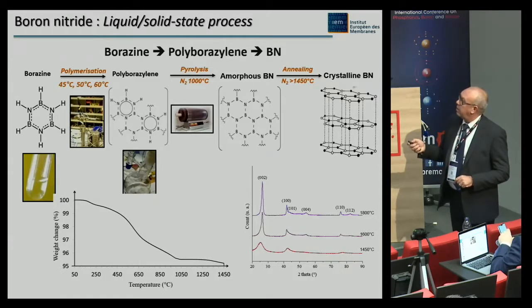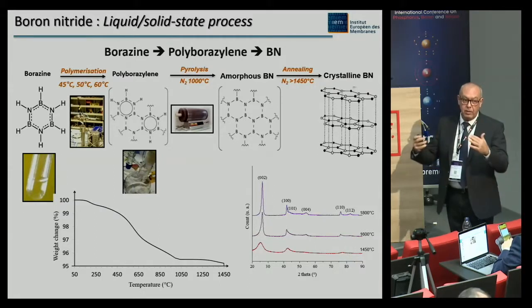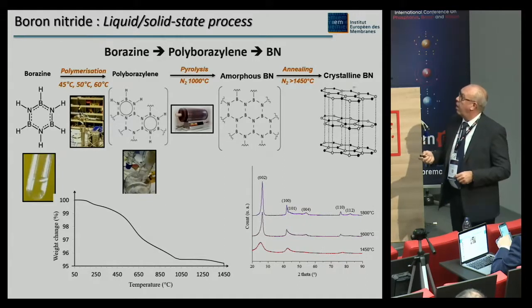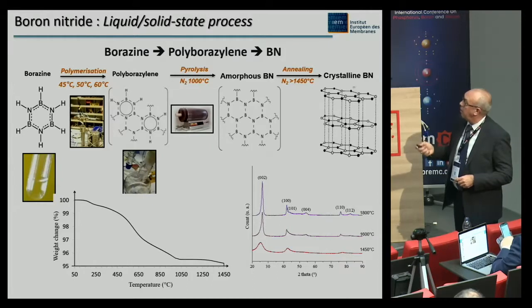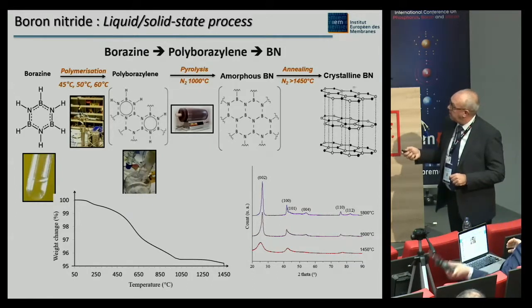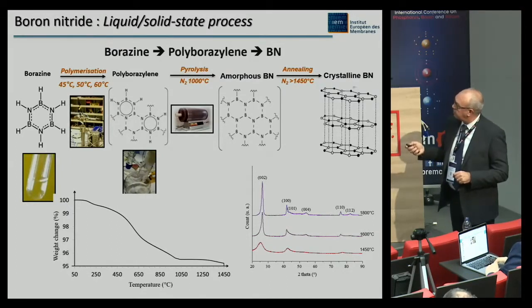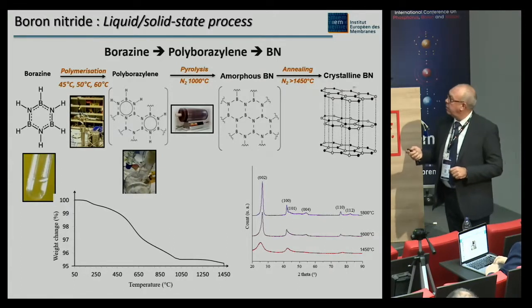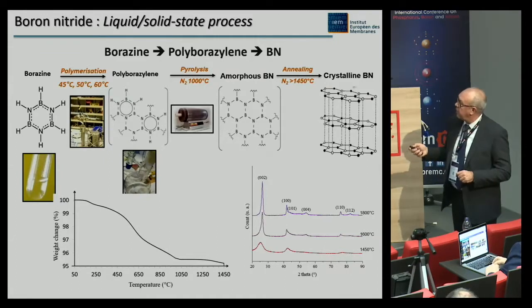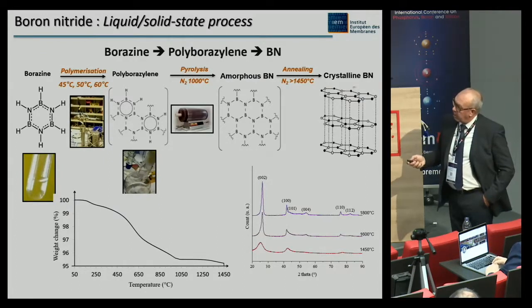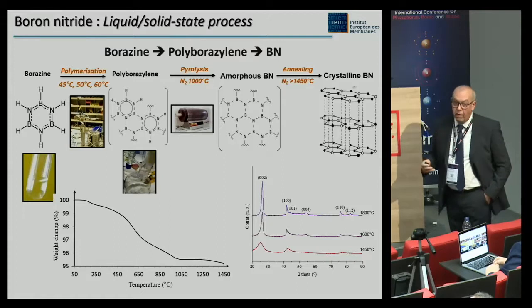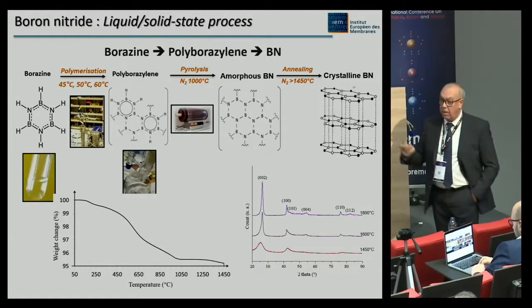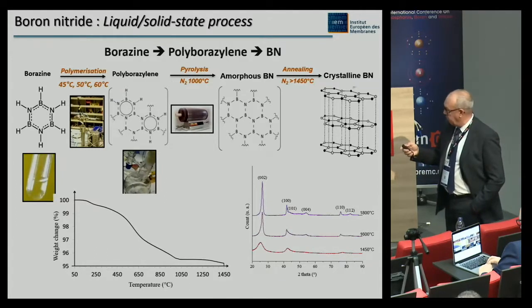And by pyrolysis under nitrogen up to 1000 degrees, you obtain this amorphous BN ceramic, which can be crystallized at higher temperature, up to, let's say, above 1500 degrees to obtain a very crystallized structure, as depicted here by the X-ray data. This is the X-ray data of the BN heat treated at 1800, showing the very good crystallinity of the materials. Coming back to the ceramic yield, you can see by this TGA analysis also that the ceramic yield is above 95%, which is very, very high, as I said at the beginning of the talk.